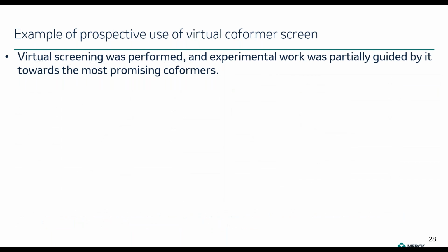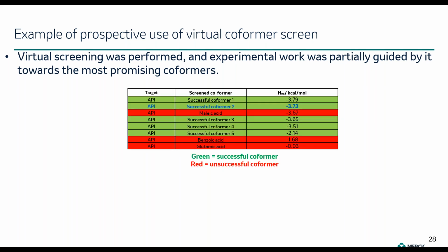So here I'm going to show you an example of how we use this prospectively. So in this case, there was interest in finding a co-crystal of a given API molecule because the single component crystal structure had suboptimal properties. So we performed a virtual co-crystal screening ahead of the experimental work, and the experimental work was partially guided by this virtual screening towards the most promising coformers. So in this table, I show some of the coformers that were experimentally screened. And as you can see, those at the top of the list are in green, were successfully co-crystallized with the API, and those in red were failed experiments.